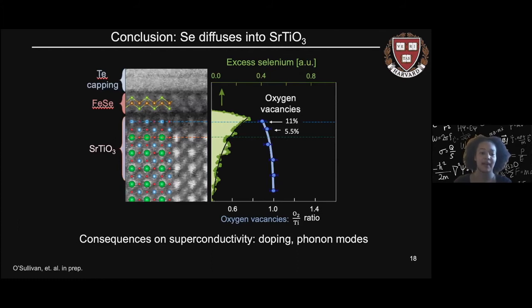In summary, today I've presented our experimental results, which attempted to answer the question: is there selenium diffusion into the strontium titanate bulk, even though we do not observe an ordered layer of selenium at the interface? And the answer to this question is yes, we do observe selenium diffusion several unit cells into our strontium titanate bulk. Moreover, the selenium diffusion is accompanied by oxygen vacancies, which we can quantify at 11% and 5.5% in the top two layers of titanium dioxide, respectively.